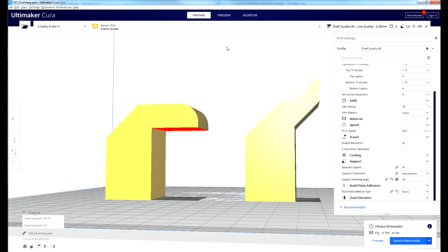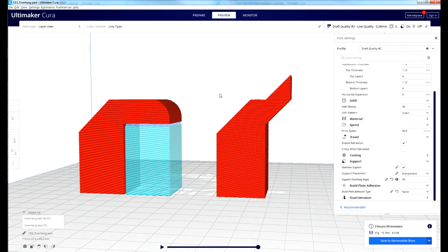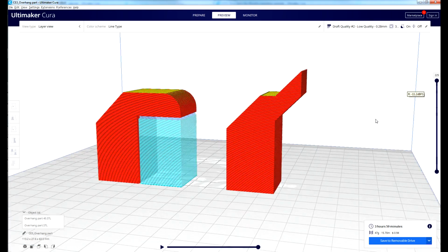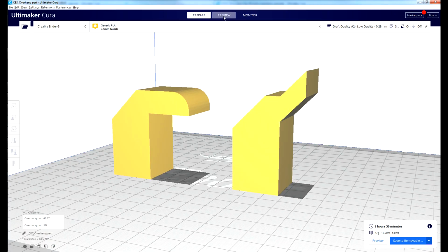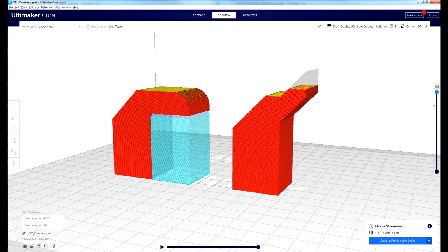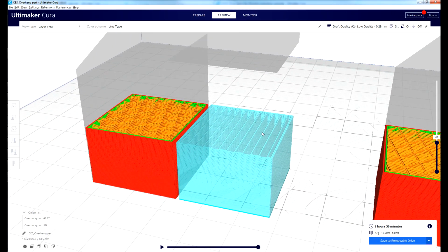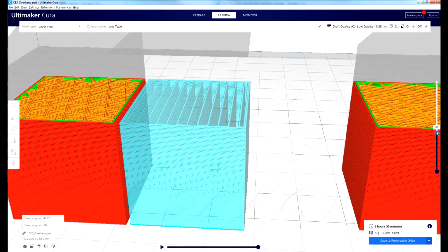Of course, there are exceptions, and this is referred to as a part's overhang. A modest amount of overhang can be printed without support, and this is usually limited to about 45 degrees. Slower printing is better for parts with lots of overhang. Features that exhibit overhang are usually marked in red by the slicer. Adjusting a part's orientation can help minimize the need for support structures, but sometimes supports are inevitable. Support structure is a sparse density filler that breaks off easily from your model. We'll talk more about overhang and supports in a bit and some advanced features.